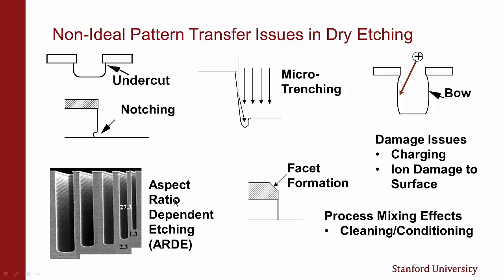Lastly, there are process mixing effects. If one process follows another, there can be interactions, because etching byproducts can deposit on chamber walls and affect subsequent chemistry. Remember, plasma etching is a chemical reactor and the wafer is just one surface — the walls also play a role. Any chemistry recombination at the wall affects radical concentrations and even plasma density. This is why we do plasma cleaning and conditioning before a process — to get wall chemistry in equilibrium so we get the same radical concentration at the wafer each and every time.